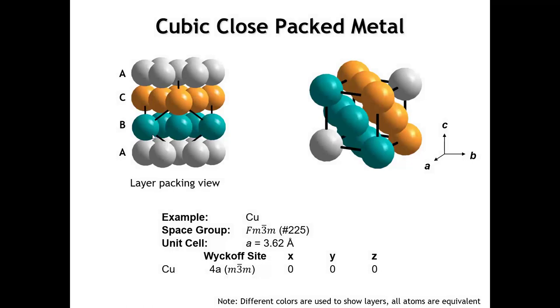Now, how do we get the cubic unit cell from these hexagonal layers? And the key thing to remember is that in a cube, there is a three-fold rotation axis along the body diagonal. So then it makes sense that if we were to look at the direction normal to the layer stacking, A, B, C, A, B, C. That's the vertical direction in this drawing. That would be the three-fold axis of our cubic unit cell.